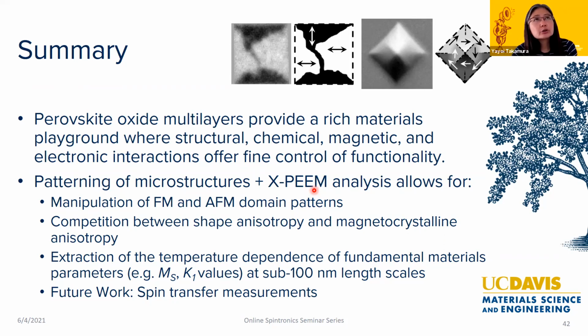So 2 nanometers is the thickness of your film, and you want to know whether you have enough sensitivity to measure the magnetic signal from PEEM. Is that your question? For our work, we have a base layer, a 6 nanometer continuous film, but the top layer we pattern into nanostrips. That means the base is probably still in the normal strain state for LSMO on STO, but the top has different anisotropy. Okay, now I remember the work.